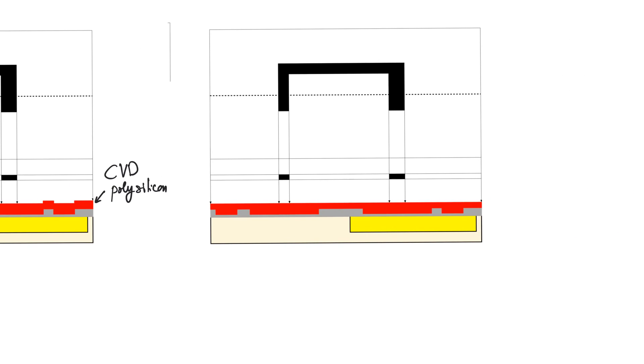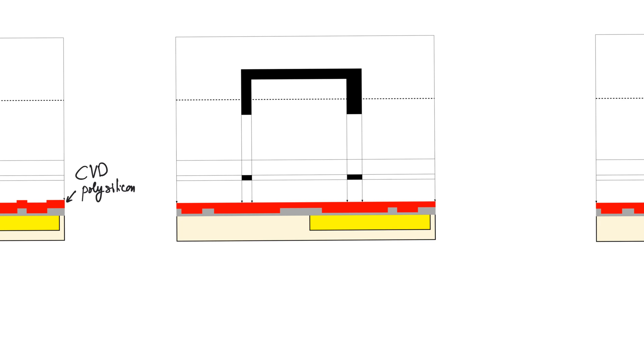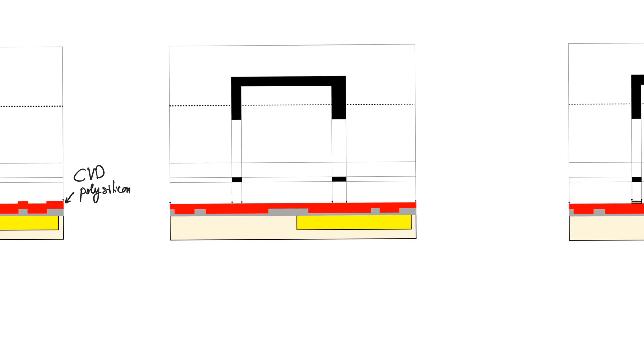We have to use chemical mechanical polishing to completely polish the surface of the polysilicon. If we don't do this, then when we use etching to pattern the polysilicon it will not give us accurate results, because it will take longer to etch the thicker parts and shorter to etch the thinner parts. More importantly, if we don't planarize the polysilicon at this point, the irregularity will build up in higher layers and we will end up with faults or defects in the form of unplanned opens or unplanned shorts. In any case, we end up with a well-planarized layer of polysilicon.